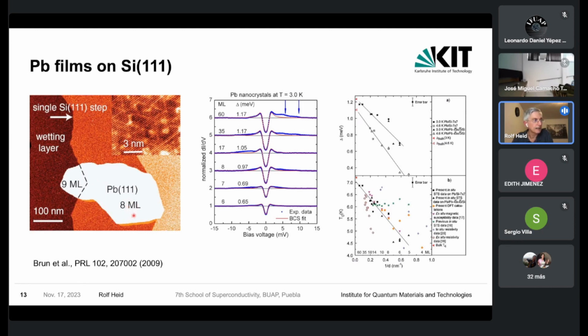And the high control of such islands, which are essentially atomically flat, allowed the study of the superconducting properties of such islands in great detail, in particular as a function of the monolayer thickness. And one has found that, for example, in this tunneling spectra, which shows essentially the superconducting gap, this gap is reduced when you go to thinner and thinner films. Similarly, the superconducting transition temperature also reduces from the bulk value to lower values if you go to thinner and thinner films.